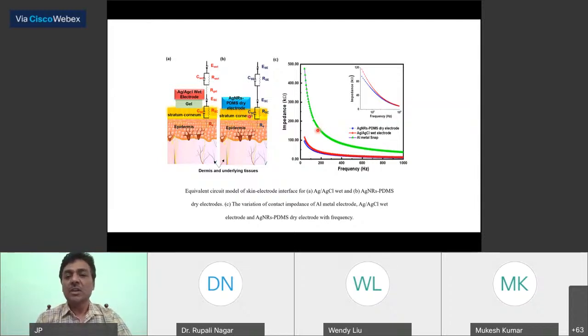So here we have compared that. You can see there is a great difference. This blue one is our curve, our dry electrode. Without using any kind of conducting electrolyte, we were able to achieve impedances which are much lower compared to the commercial one.